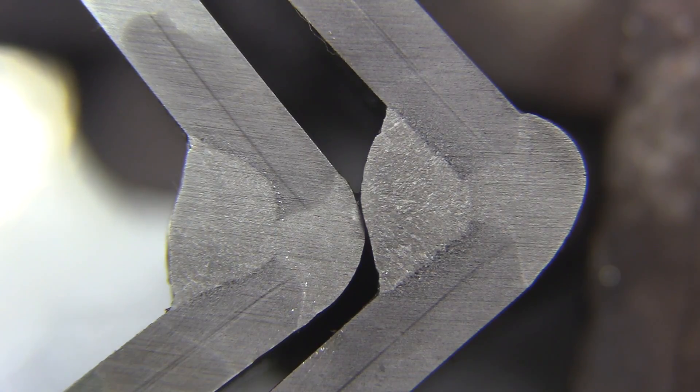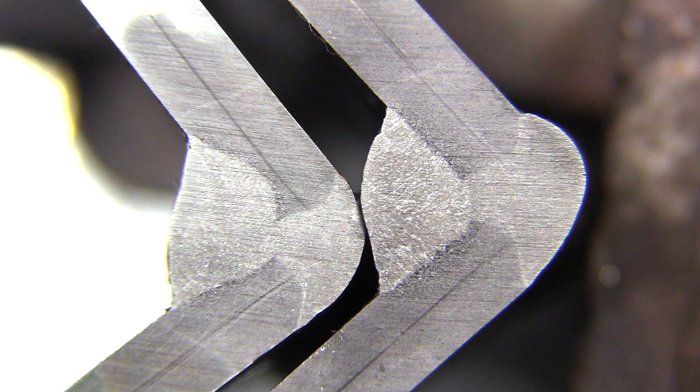The more you polish the more detail you generally see. I took these down to about a 400 grit polish so you can see some details. You can see those lines in there which are something apparently called solidification segregation and you generally don't want to see straight lines. When I first saw this on the first one that I did a few years ago I thought it might be a lamination but I got a comment from a steel maker metallurgist who cleared me up on that.